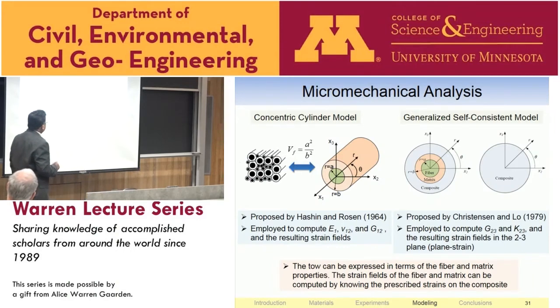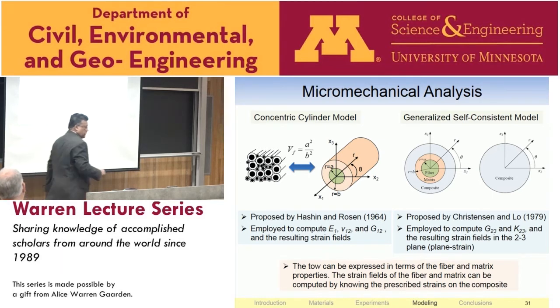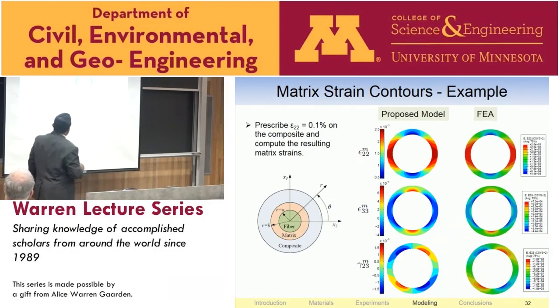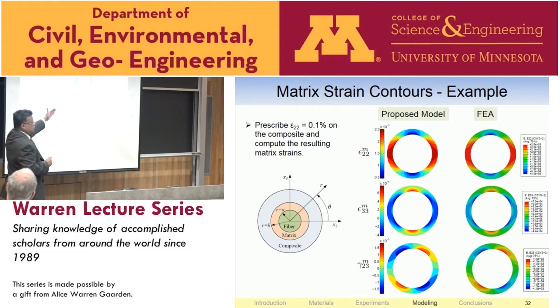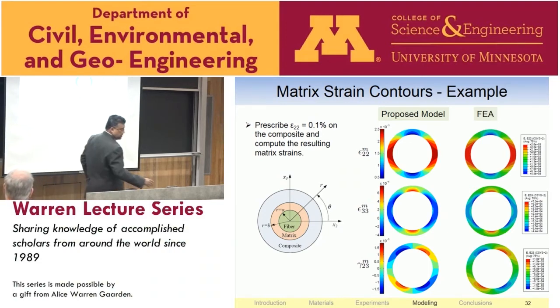So the cylinder model is shown here. And the new thing here is that this model has been used in the composites literature for a while. What's new is that instead of just using it to find instantaneous properties, we actually solve for the strain and stress fields inside the cylinder. So given the state of strain outside the cylinder, which is coming from your macroscopic calculation, we solve for the states of strain and stress inside the cylinder, right? And so we checked it against a full 3D finite element model for that. And you can see that the contours match very well, and we get very, very good agreement, the analytical approach we are taking in a closed form sense.